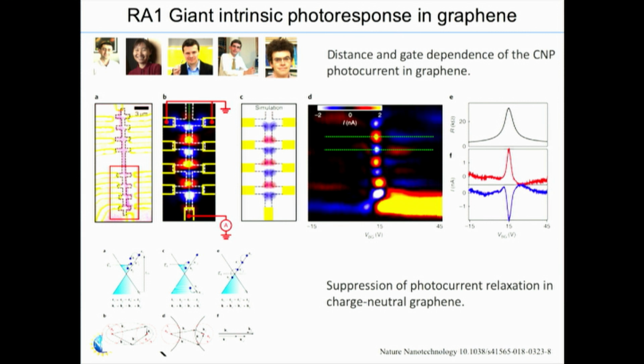And so it's a funny kind of photocurrent, but it opens up a new way to make devices where, if you make the shape of the material have a particular kink in the edge, you can create a current that's coming out of that kink that will go for many microns in that direction, which is sort of totally counterintuitive.